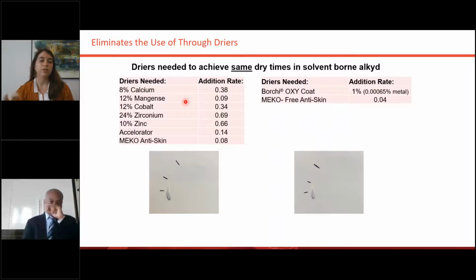Which brings a faster curing time. So they had manganese, cobalt, zirconium, zinc, also an accelerator or chelating agent, as well as calcium. In this case, we were able to remove all of these carboxylates out of the system and find equal curing time with just our Borchi OXY Coat, both containing an anti-skinning agent.